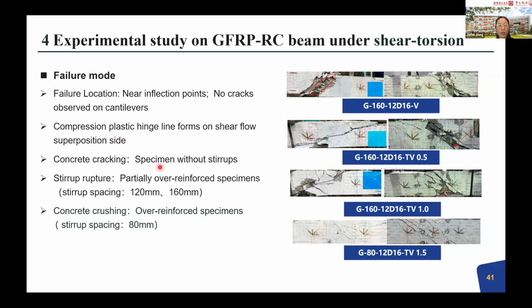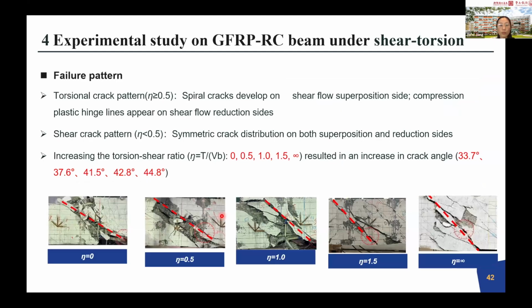For concrete cracking, for specimens without stirrup, we only observed typical cracking. But for beams with stirrup, we have multiple cracking, and we also found in the partial over-reinforced failure mode that stirrup rupture and also concrete crushing can be found in this type of testing. And also we see that the cracking angle, from pure torsion to pure shear, ranges along this value range. This is for pure shear, and this is for pure torsion.